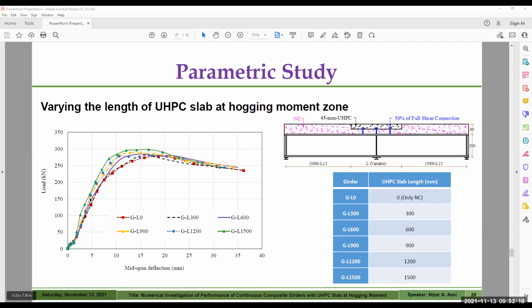But during the ultimate stage here, there is no significant enhancement in the behavior of the composite girder with different lengths. So we can conclude that the length of the UHPC slab enhances the performance of the girders during the service life of the girders, not during the ultimate or failure conditions.